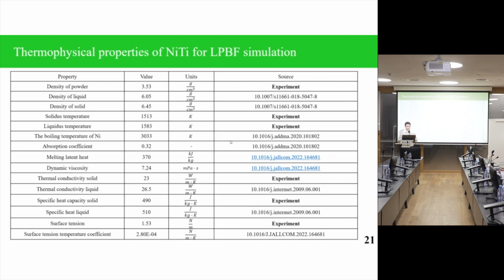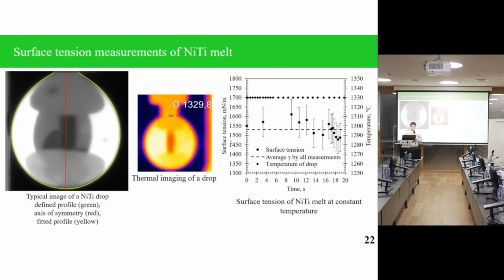Each simulation starts from thermophysical properties, and there is a lack of thermophysical property data for nitinol that are required for the melt pool simulations, so some data was obtained experimentally. The most important experiment was done to measure the surface tension of nitinol melt. This is the pendant drop method. Inside a graphite heater, the nitinol melt was formed, and from a graphite dropper, the drop was squeezed, and based on measurements of the profile, the final value of surface tension was obtained, and it was used in the further simulation.